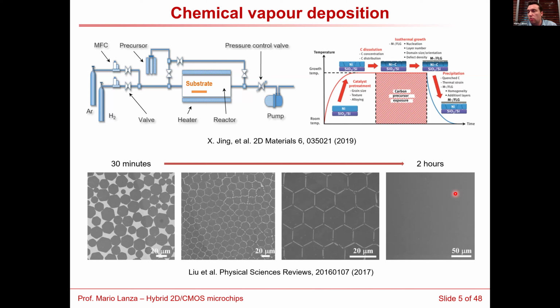For some applications, they will be okay, but for ultra-scale devices, it's very different. So the method that is preferred by the semiconductor industry when working with 2D materials is chemical vapor deposition. It consists of a heating chamber, normally a tube, where one substrate is placed. Then there is a precursor and a carrier gas. By opening some valves, these two things can be introduced into the chamber, and at high temperature, after some time, the material can be grown.